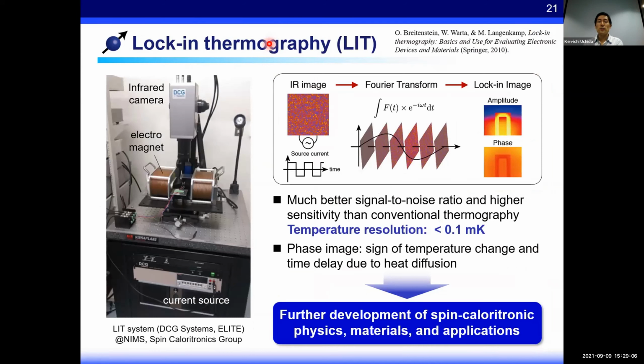This method provides a much better signal-to-noise ratio and higher sensitivity than conventional thermography. During the measurements, we apply a periodic external perturbation to the sample and extract the first harmonic response of the thermal images oscillating with the same frequency as the perturbation. The obtained thermal images are converted into lock-in amplitude and phase images by Fourier analysis. Here, the amplitude image shows the distribution of the magnitude of the temperature modulation induced by the external perturbation, and the phase image provides information about the sign of the temperature change, as well as the time delay due to heat diffusion.